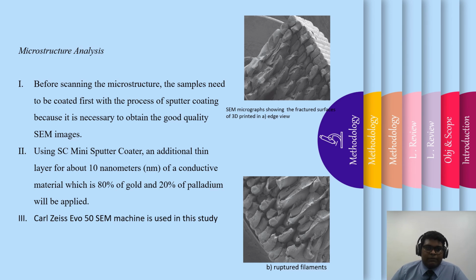After the mechanical test, the specimen must undergo microstructure analysis. Before scanning the microstructure under SEM, the sample needs to be coated first with a process of sputter coating because it is necessary to obtain a good quality SEM image. The sputter coating is conducted using an SC mini sputter coater. After applying the coating, the specimen will be scanned using the Carl Zeiss EVO 50 SEM machine to examine the microstructure.